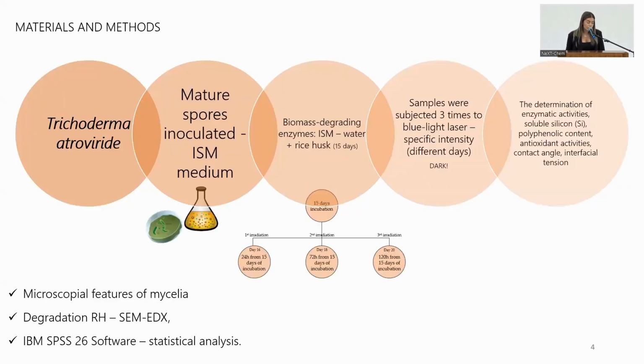The strain that we used was Trichoderma atroviride. Fresh mature spores from ISM medium were used to stimulate the production of biomass-degrading enzymes and were cultured in water supplemented with rice husk in 2-liter flasks for 15 days at 28 degrees Celsius. The samples were exposed 3 times to blue laser light for 60 seconds each at a specific intensity on different days. All the flasks were kept in the dark throughout the experiment.